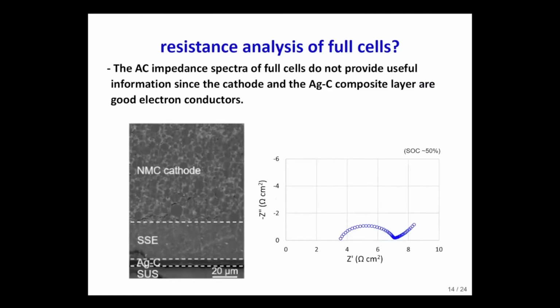The first thing we can think about is the AC impedance analysis of a full cell. But the cathode is a good electronic conductor, and the silver carbon layer is also a good electronic conductor. So if we take the full cell AC impedance, then we can get only the information on both sides of the solid electrolyte layer. So it's not going to reveal the information inside the cathode.